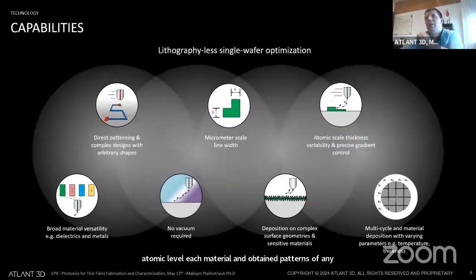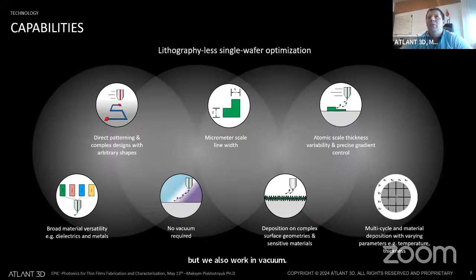So today the technology has several critical capabilities: direct patterning, local deposition, broad selection of materials. It doesn't require vacuum, but we also work in vacuum. Micrometer scale line width. We recently demonstrated a few micrometer line width. Since it's ALD, it can work on very complex surfaces, not only flat wafers, but membranes and nanostructures. And it allows processing across the whole value chain, from material processing to scalable manufacturing.